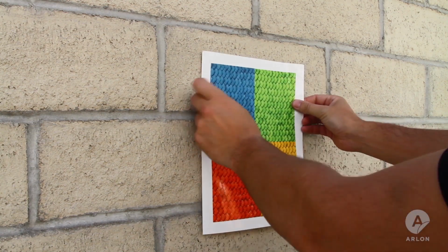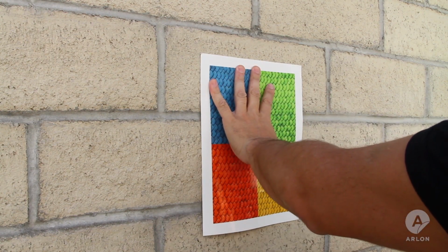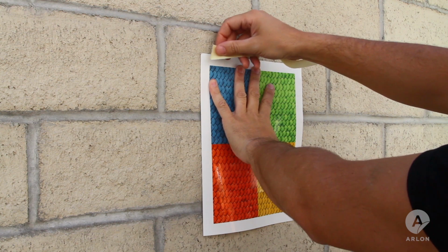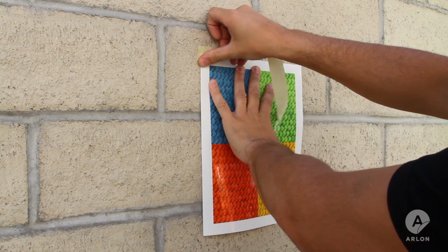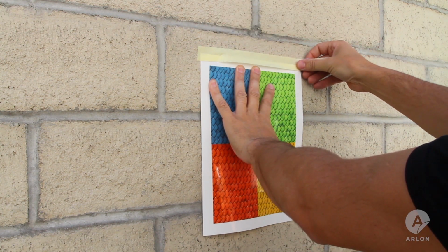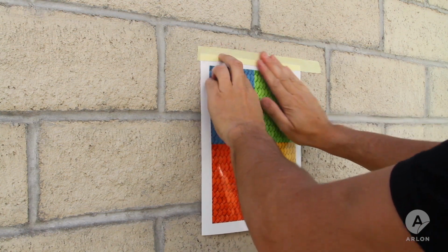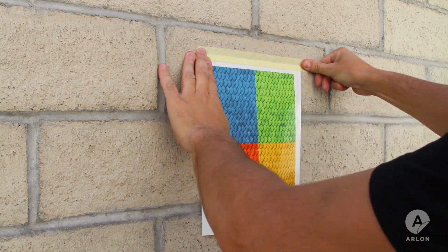Sometimes dry cleaning a wall just isn't enough. Some walls found in public areas like subways need to be power washed. If you're going to power wash a wall, make absolute sure that it is completely dried before you try to do the test. If you are not sure which media you should use, always test all of your options side by side to see which performs the best. A4 size samples are perfectly sized for this kind of test.